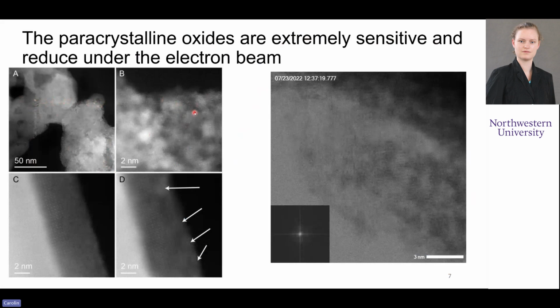And when you look at it, you can see all these tiny crystallites that have formed all over this area. And even on the perovskite surface, on the left here, you see basically the first frame that was captured in this area, and you can see this surface layer that looks pretty much amorphous. And already on the second frame, you start to see the changes and the first aggregations and lattice fringes that start to show up here.